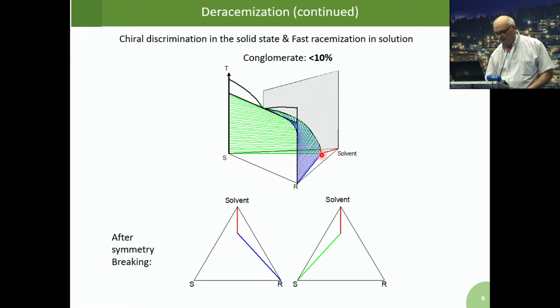Okay, so the only thing that you have is the intersection of that racemic plane with the saturated double solution which is there. And then you start by a system which has one enantiomer and another enantiomer here, and with this racemic plane. And by applying this flux of energy in the suspension, you will have this irreversible evolution towards one enantiomer or towards the other. And this is stochastic if you don't have any impurity, chiral impurity inside.